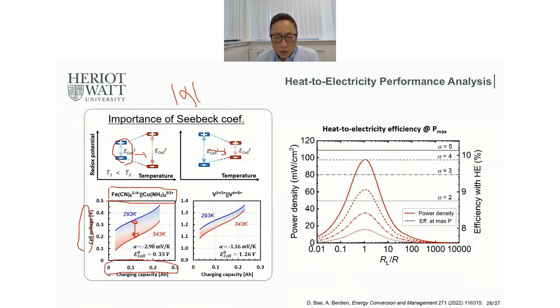But the disadvantage is they only have a cell voltage of 0.3 volt. So if we use this system, we can have a high cell voltage difference at the different temperature conditions, but the overall system power will be quite low. How about the vanadium case? Using the conventional vanadium redox system, we can have a very narrow gap between the cold temperature and the high temperature condition. But the good thing is that their cell voltage is pretty high.